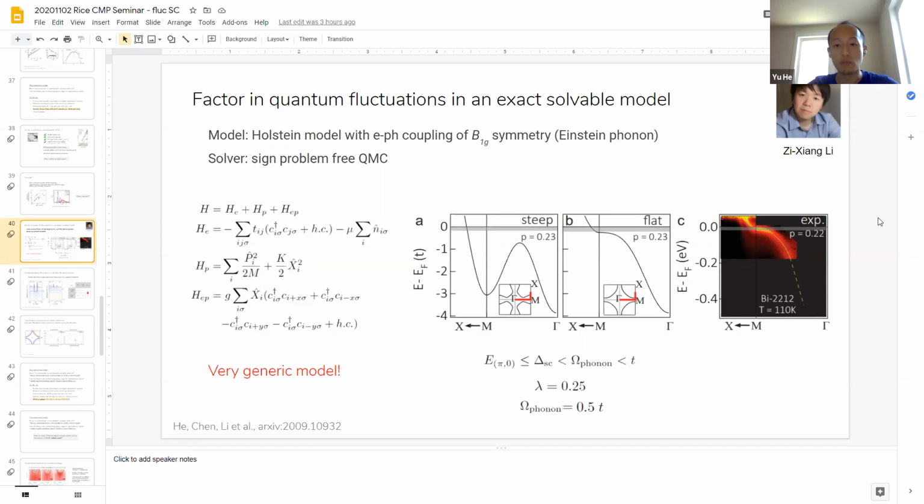So with that in mind, we can first already have a physical intuition by looking at the Fermi velocity. In those partially flat shallow bands, the Fermi velocity is really, really low. So even if we were to just come from textbook BCS, that will give us a really, really short correlation length. And a shorter correlation length gives us a much smaller correlation volume, and thus a very small number of Cooper pairs, if overlapping at all, within that correlation volume. Therefore, there is an innate tendency to have stronger fluctuation, even just from arguing from the BCS picture.